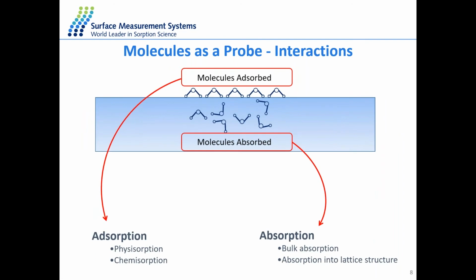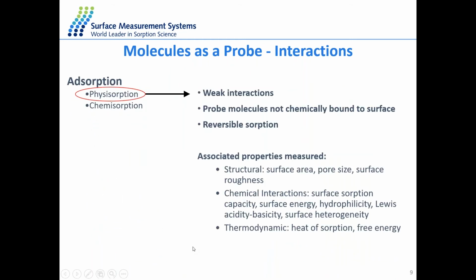When we talk about molecules adsorbed on the surface, it can be either by physisorption or chemisorption. Physisorption is a kind of weak interaction where the probe molecules are not chemically bonded on the surface, and it's more like a reversible process. The properties we can measure with physisorption are more like surface properties, for example, the surface area, the surface energy, pore size distribution, or heat of sorption.